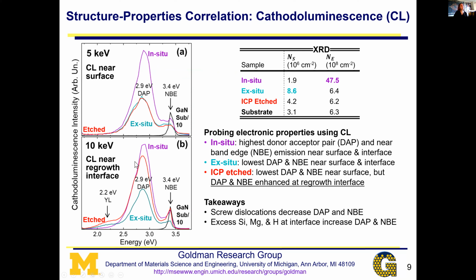And so at this interface, once it recovers some of its electronic properties, it trends exactly the same as the trend we see in the screw type threading dislocation densities. The ex situ had the highest screw type TD density, meaning the worst crystallinity. The crystallinity was better for the ICP etched, and then the best for the in situ. And that's the same trend that we see here with the donor acceptor pair emissions at the interface. The ex situ had the worst, we see improvement with the ICP etched, and then the in situ had the best.